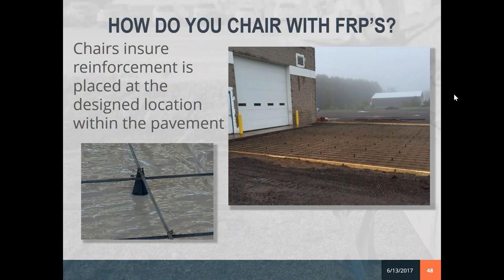Again, here it's very important to put chairs up underneath your reinforcement. A lot of times that reinforcement ends up at the bottom of your pours. The laborers reach down, they pick it up, and you have no idea where it is. Another advantage, if that does occur and the laborers pull it up and it's only an inch from the surface, it doesn't begin to corrode and rust. It'll make the concrete a lot more durable, whereas with steel, moisture begins to attack it, not immediately, but down the road at some point the corroding rebar will start to spall off. So with FRPs, that potential is eliminated if it is close to the surface.